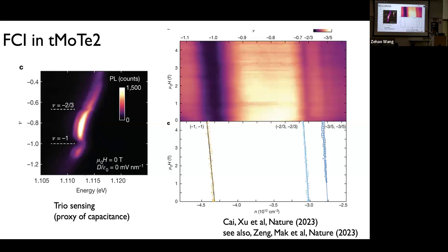And later, they expanded this experiment as a function of magnetic field, and you can see that there are 3 features, and each of them disperses as a function of magnetic field. Careful analysis tells you that the leftmost one is -1, and then it's -2/3, and then -3/5. The really exciting thing is that all these data points, at least for the 2/3 and -1, interpolate and persist down to 0 magnetic field. So this is already a good sign that you have FCI at 0 magnetic field.